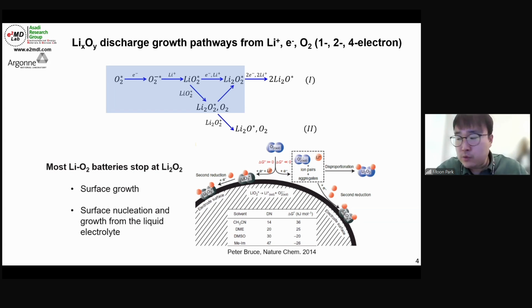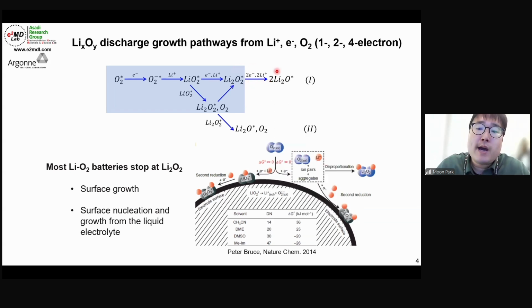However, it has been known that most lithium-oxygen battery research shows only either lithium superoxide or lithium peroxide, because the last step involves 2 moles of electrons and 2 moles of lithium, so it requires a higher energy barrier. So far, it has been known that at room temperature it is not possible to form lithium oxide, and not possible to do the 4-electron reaction.